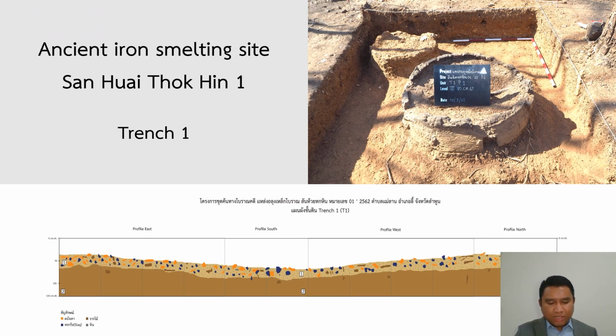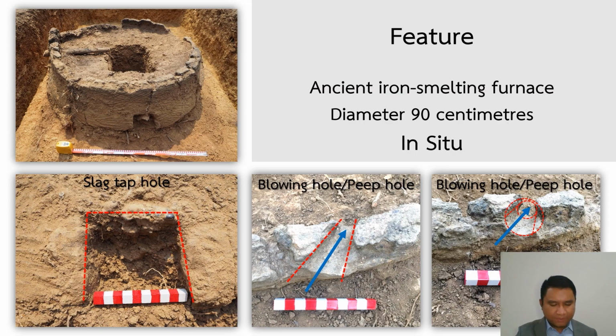This is two in situ iron furnace structures, which were found in San Huai Thok Hin number 1 site. The soil profile represents the smelting activity was in process for a short time. The smelting layer is only 30 cm deep. Let me show you an in situ shaft furnace. The diameter is 90 cm, and the furnace wall has a blowing hole which has an exit tilted at 30 to 45 degrees. On the bottom of the furnace are 4 slag tap holes.